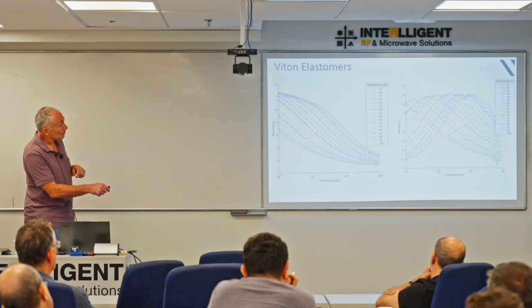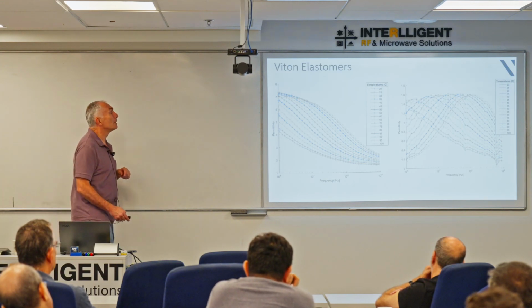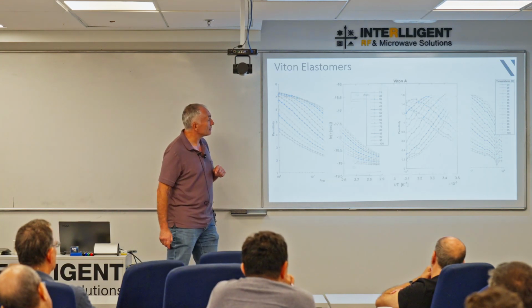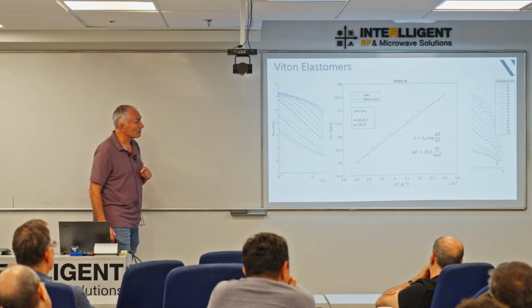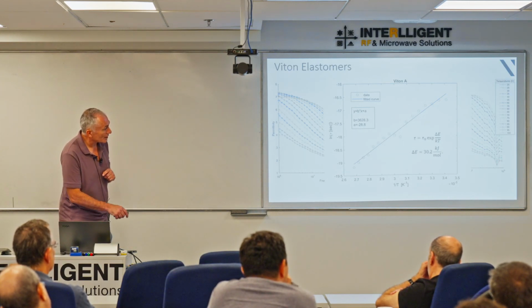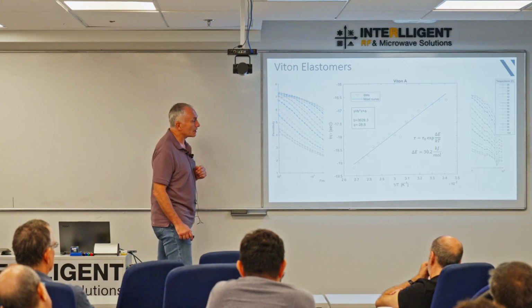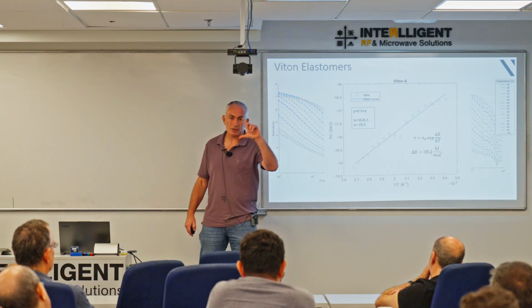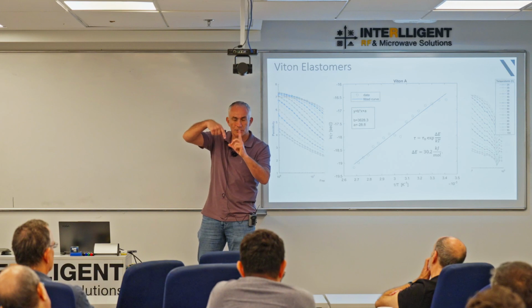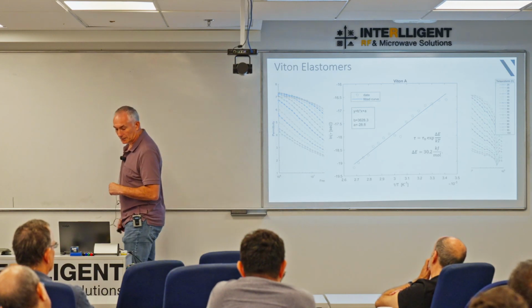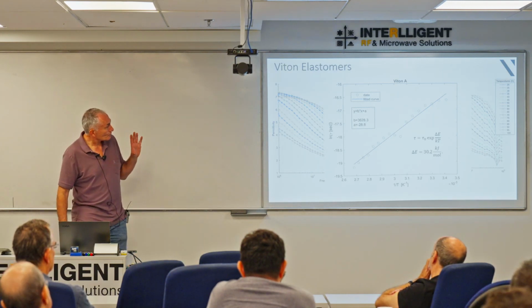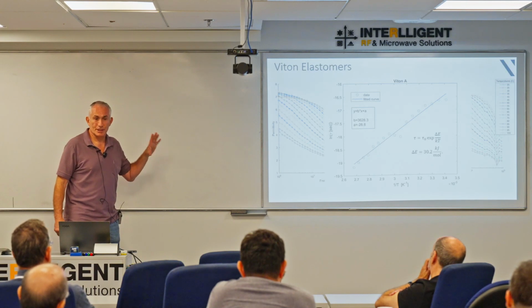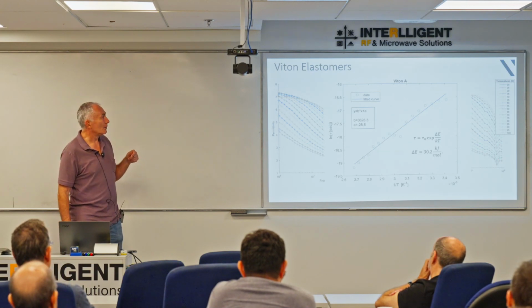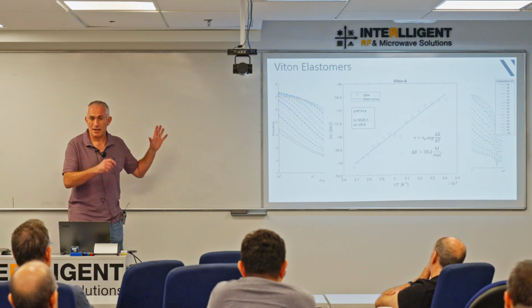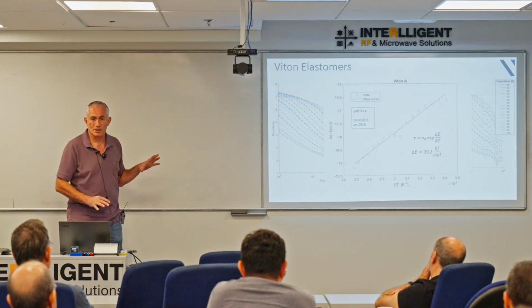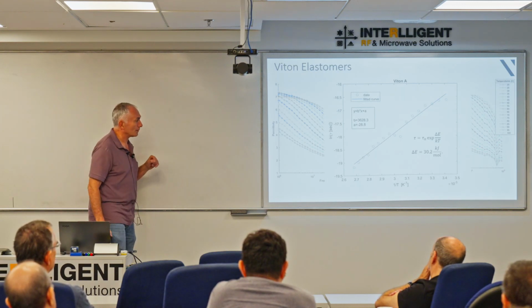Now, we changed temperature on this one, and you can get from there an energy of activation, and there's the energy of activation that we can get. It's about 30.2 kilojoule per mole, which tells us something about how it's actually linking up, how much it really is involved in cross-linking. So you can go a lot deeper into this, and you can get a lot more out of this. And I haven't actually shown too much of the higher frequencies we can do with plastics, but you can go a lot deeper.